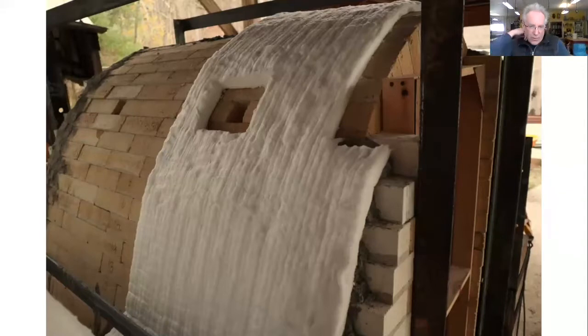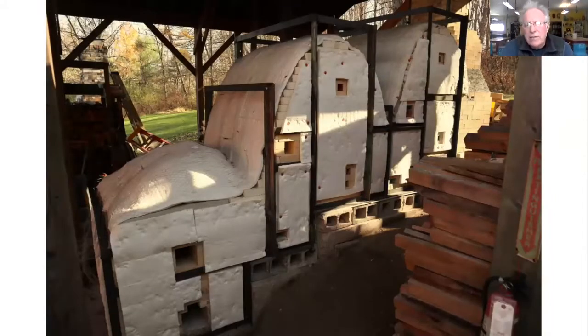After all of the refractory brick is built and put in place, then the kiln is covered with this kaolin wool blanket. Kaolin wool is a high temperature refractory that was invented for the space shuttle at NASA and was the backup for the insulator behind the tiles on the space shuttle. In its early days, it was too expensive for potters to get their hands on, but now it's roughly the same price as an insulating brick. So it's highly insulating and goes on there in place of putting another layer of insulating fire brick on the kiln. The fiber blanket is attached with nails.